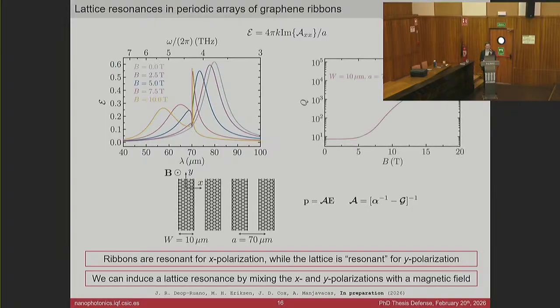And we can see that if we plot the quality factor against the magnetic field, once we are able to sustain a lattice resonance around 7 Tesla, the quality factor increases by several orders of magnitude. And the same for some other cases that I studied.